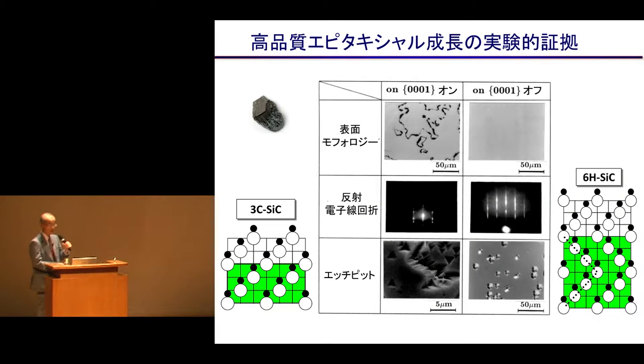So we had a reactor that we made that we used for this research. And so you see the natural surface here. And we put an angle here and attach it to the surface where it's polished. Then if we observe the surface morphology, it becomes very smooth and shiny. And so we always find this mosaic pattern on the surface. In the Acheson crystal, an industrial material, the white is silicon and the black is carbon. And there is this repetition forming a zigzag pattern, and it goes back every 6 times. Compared to that, in the case of silicon or gallium arsenide, there's only a single direction.